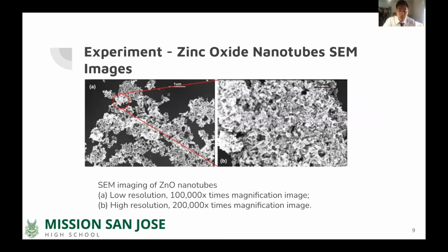Low conductivity makes it difficult for lithium ions to disperse through the materials. As shown in this figure, zinc oxide nanotubes are tested by SEM. If we look at the low resolution image of only 100,000 times magnification, it can be seen that the distribution of nanotubes is roughly uniform. There aren't too many large clumps of nanotubes, which would decrease their effectiveness. From the high resolution 200,000 times magnification image, we can see that the length of the nanotubes ranges from the shortest at around 50 nanometers to the longest at around 250 nanometers. The width of the nanotubes is around 15 nanometers, which makes the aspect ratio around 5 to 15.